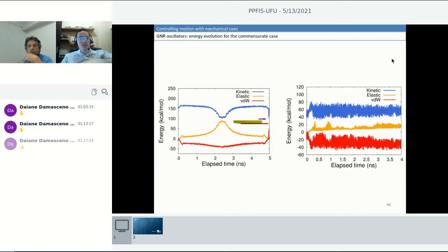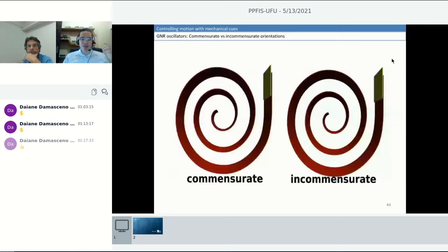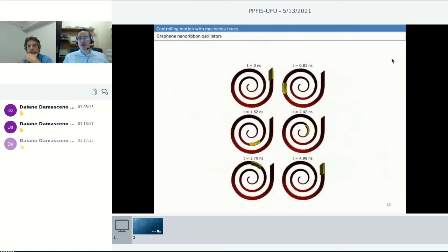If we put the thermostat on this nanoribbon that's moving very fast, it's translational kinetic energy, not really temperature, but the thermostat treats it as such. So we launch it very quickly, and it won't even collide with the substrate. What I was trying to avoid in the simulation is the thermostat removing this translational energy of the nanotube and the nanoribbon and stopping the movement too quickly.